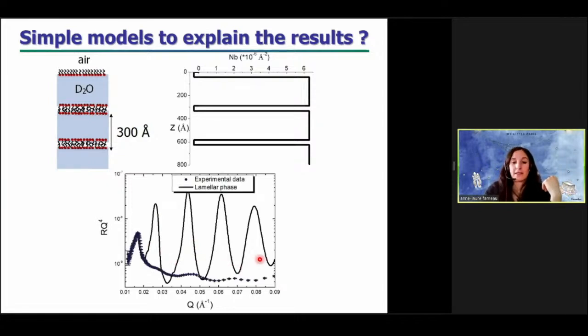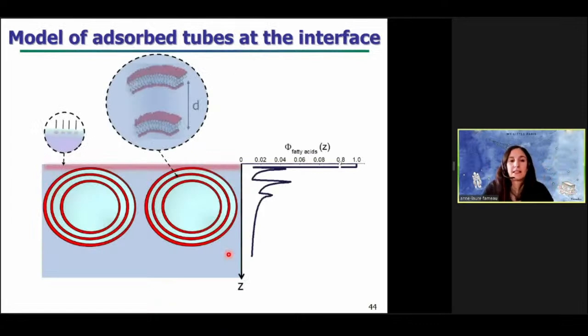Then we compare this lamellar phases model with our experimental data in blue. And as you can see here, the two curves are very different. The interference fringes are far too high in the case of lamellar phases at the interface. So that clearly shows that tubes are not unfolded at the interface to form simple lamellar phases. So then we decided to model the adsorption of tubes at the interface.